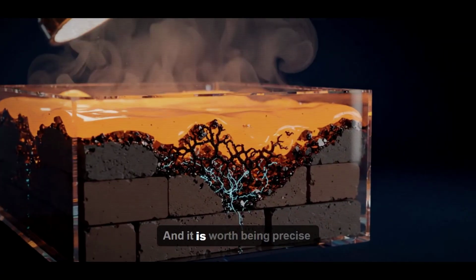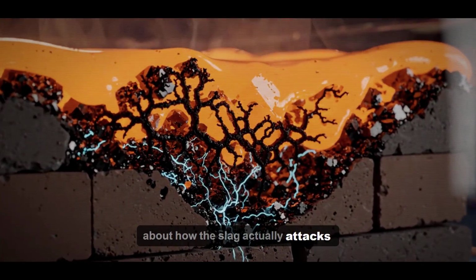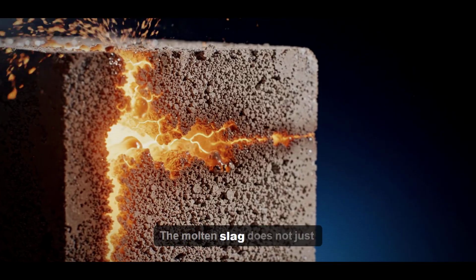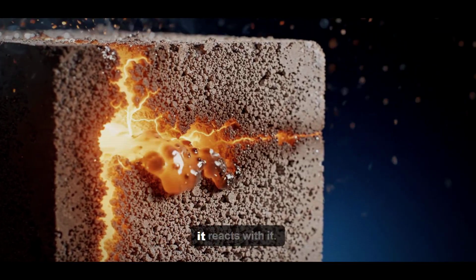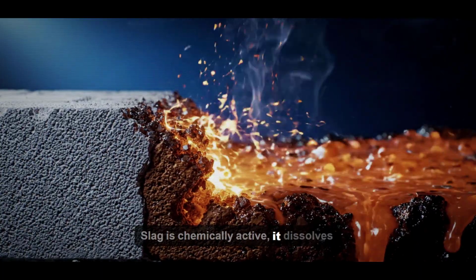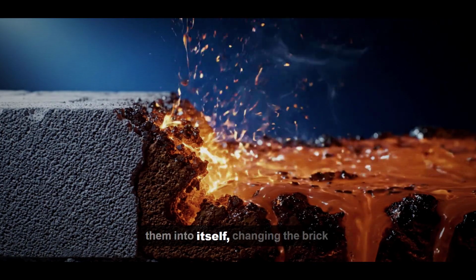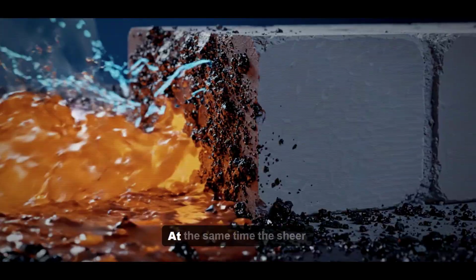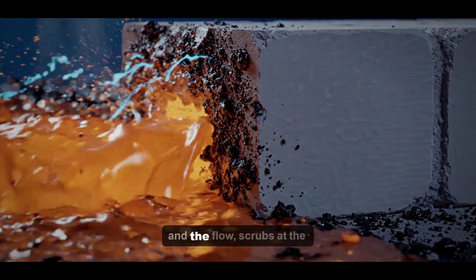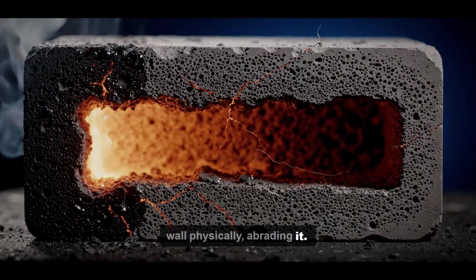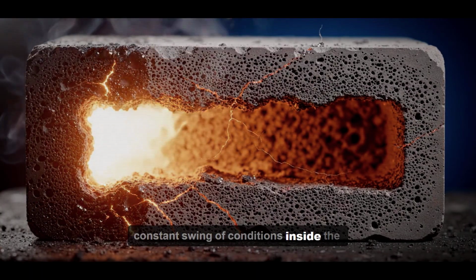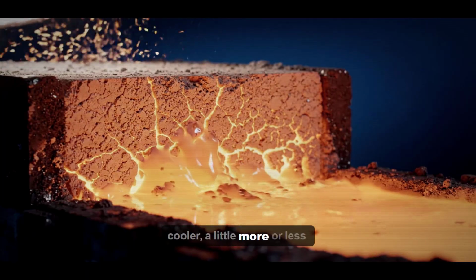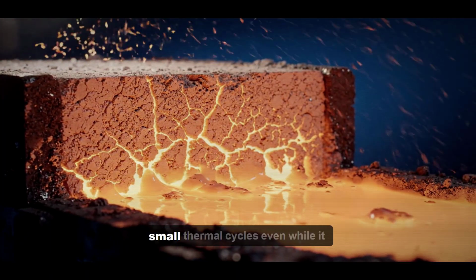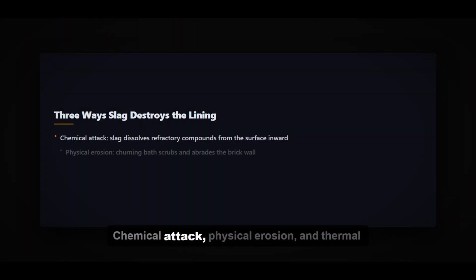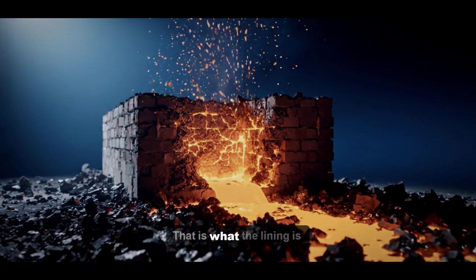And it is worth being precise about how the slag actually attacks, because it is not simple melting. The molten slag does not just heat the brick until it softens, it reacts with it. Slag is chemically active. It dissolves the compounds in the refractory, pulling them into itself, changing the brick from the surface inward. At the same time, the sheer motion of the bath, the churning and the flow, scrubs at the wall physically, abrading it. And on top of that, the constant swing of conditions inside the furnace, a little hotter, a little cooler, a little more or less slag, puts the wall through endless small thermal cycles even while it is running. Chemical attack, physical erosion, and thermal cycling all working on the same brick at the same time. That is what the lining is standing in.